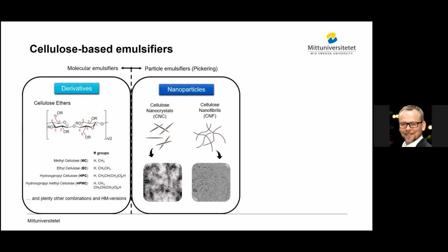And then you have particles which have also gotten some properties. For instance, on the cellulose nanocrystals, you have planes where you have more hydrophobic properties and planes where you have more hydrophilic properties. And if you have a good tuning of this sort, sometimes it happens naturally, you will have them as an interfacial layer onto, for instance, an oil droplet in water.